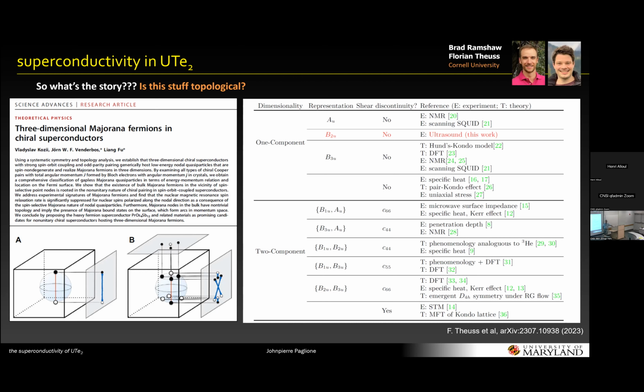Yeah, that's right. Important. And the other thing is that the penetration depth itself, the absolute number, is like a micron. So it's not an atoms-at-the-surface kind of picture. This is a response. The surface can couple with bulk, but if the bulk is already very metallic, then the contribution from the surface is going to be small. Okay, so let's continue this, but let me just finish.